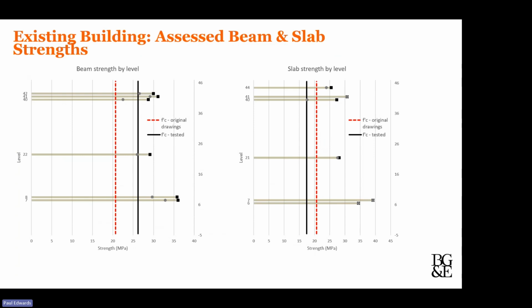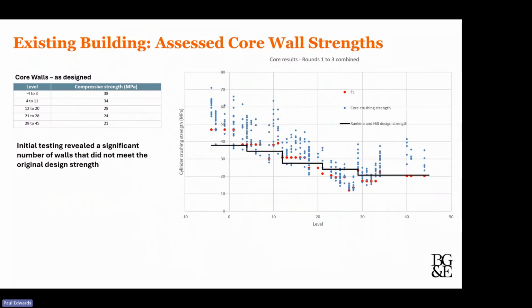Same story for beams and slabs. Generally, the existing material in the beams and slabs was found to be above minimum requirements, in some instances by a fair margin. But in terms of the cores, that core wall of which the whole core was retained, that story sadly wasn't carried through. And it's worth bearing in mind that all of this comparison with the original design strength is before any of the changes in load due to the new, taller, larger scheme come into effect.